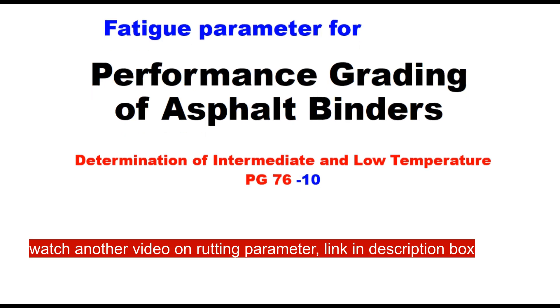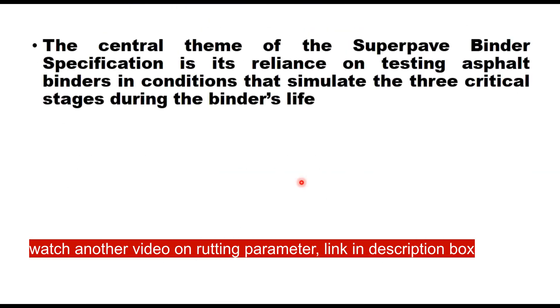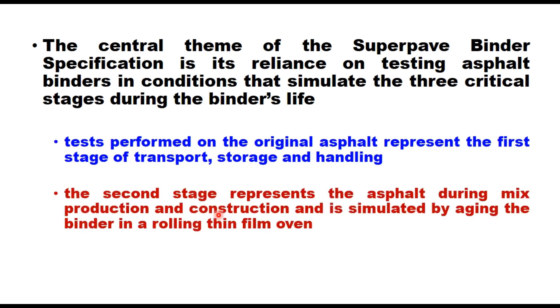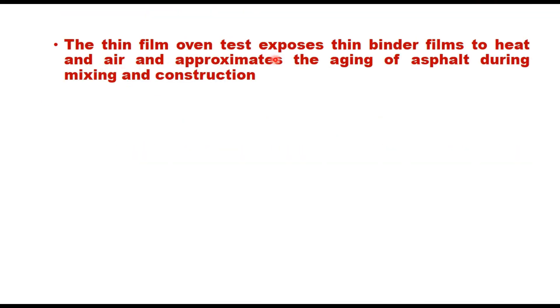The central theme of the SuperPave binder specification is its reliance on testing asphalt binders in conditions that simulate the three critical stages during the binder's life. The test performed on the original asphalt represents the first stage of transport, storage, and handling. The second stage represents the asphalt during mix production and construction, and it is simulated by ageing the binder in a rolling thin film oven, which exposes thin binder films to heat and air.